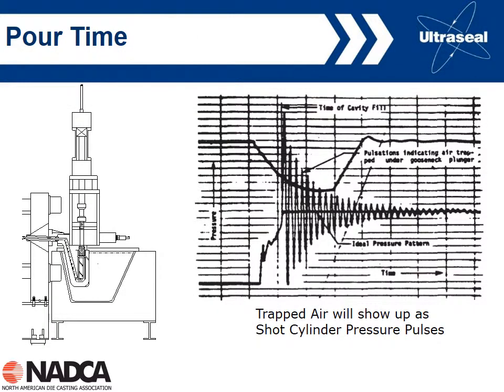So one other thing, talking about shot end pour time, this is unique to a hot chamber, is that we can have a problem occurring when we're returning the piston back to its home position and basically refilling the gooseneck with metal. What we need to do is ensure that we don't entrap air at the tip of the piston. Obviously this is bad as we could inject that air into the cavity and cause porosity.